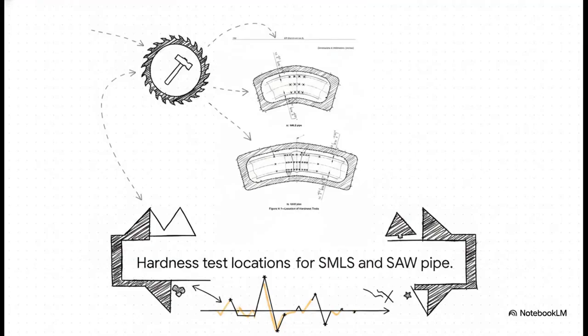Take a look at the tiny X marks across these weld cross-sections here. They mark exactly where Vickers hardness tests have to happen. Why does this matter? Well, if a specific zone is too hard, it actually becomes brittle and way more susceptible to cracking in those sour environments. So hardness cannot exceed strict limits, and the testing has to hit the parent metal, the heat-affected zone, and dead center on the weld itself.